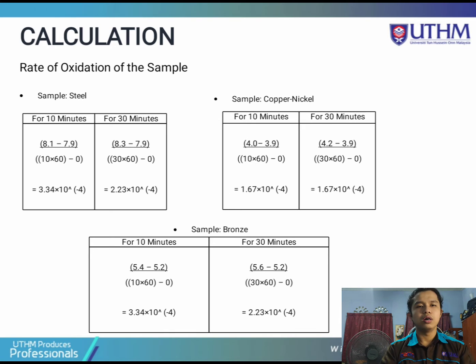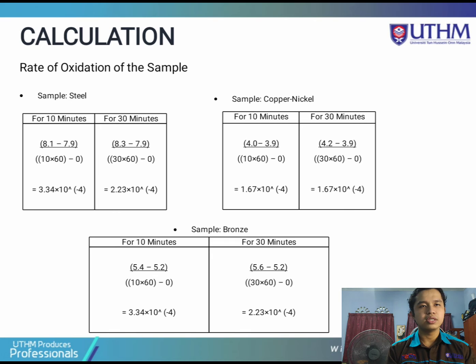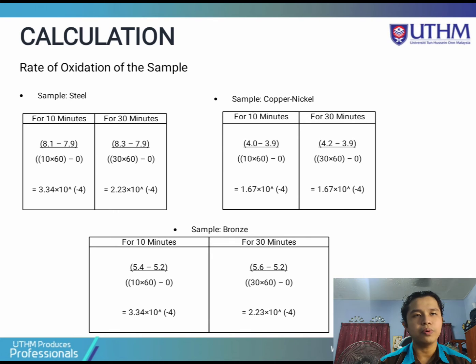For the sample steel, based on the data, we calculate the rate of oxidation by the formula: final weight minus initial weight over time in seconds. So for the sample steel, 10 minutes duration, 8.1 minus 7.9 over 10 times 60 minus 0. The answer is 3.34 exponent negative 4 gram per second. For the 30 minutes duration, 8.3 minus 7.9 over 30 times 60 minus 0. The answer is 2.23 exponent negative 4 gram per second.